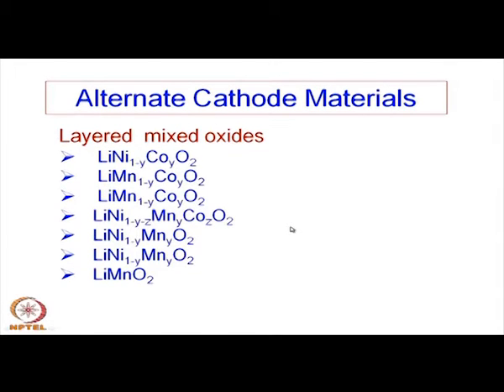Considering these materials, our attention is primarily on transition metal oxides — not sulfides, but phosphates and oxides containing transition metals. Transition metal oxides play a role because, as seen in the case of cobalt, there is a valency change from 3+ to 4+. So transition metal oxides must be the focus. Here is a list of transition metal oxides with potential application to replace cobalt oxide in the lithium ion battery system.